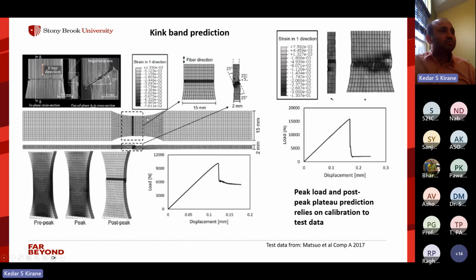And this is one of the predictions of the model with the coupon. We have some test data on out of plane kinking. So on the top left, they conducted a test on a unidirectional composite. And this is a kink band. The angle is 27 degrees with respect to the horizontal. And this is then a prediction of our model, pure prediction. This angle is a prediction, and it is 25 degrees, which agrees very well with the observations. So this is a natural outcome from the model.